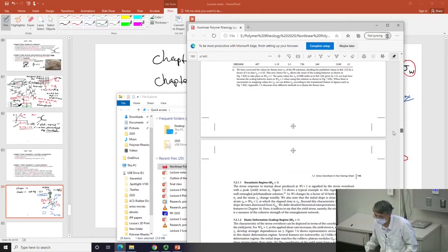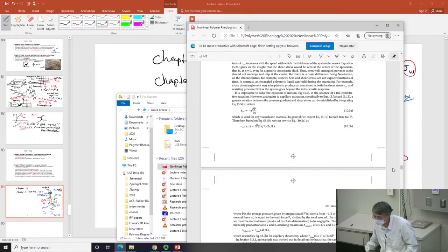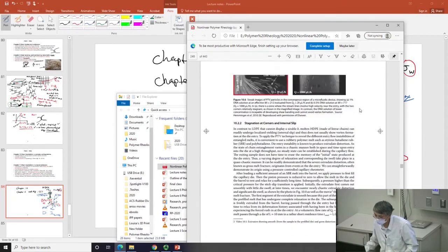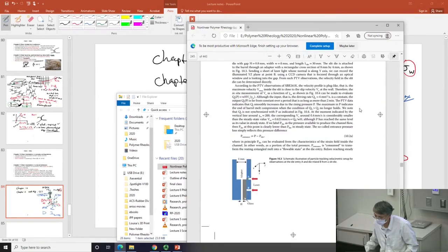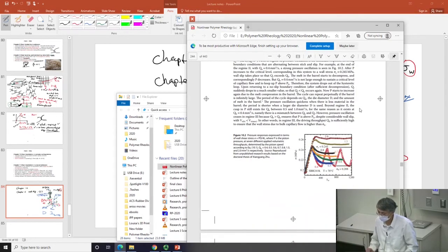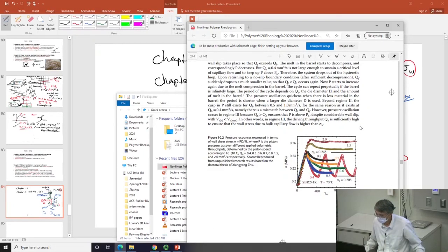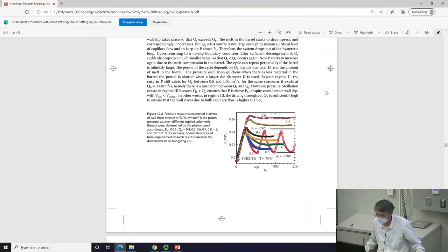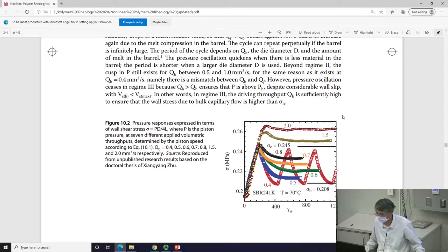That's what I observed initially when we first studied this. So for example, chapter 10, figure 10.2. If you monitor the pressure, it just oscillates back and forth. All these different curves are the different piston speeds that you put. Some are low enough, so no problem.